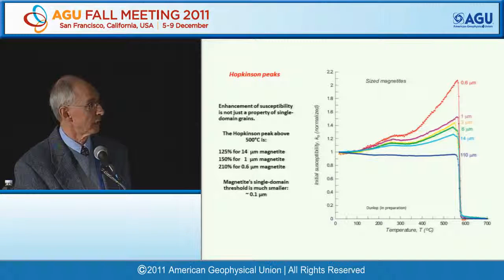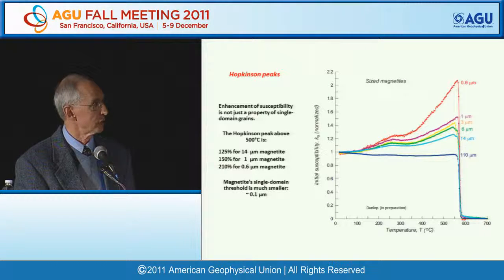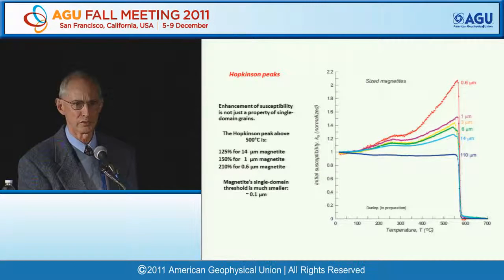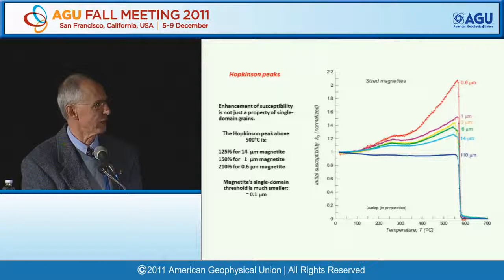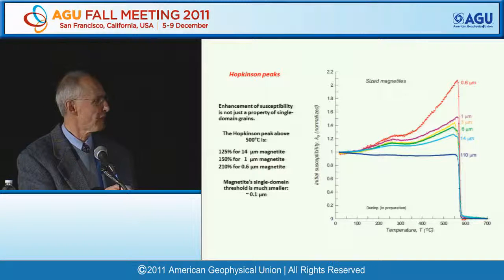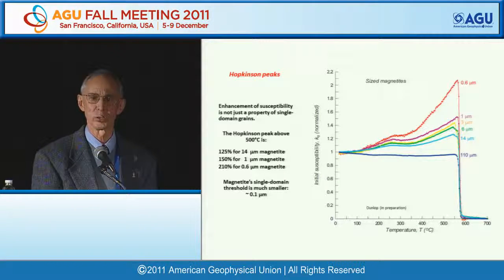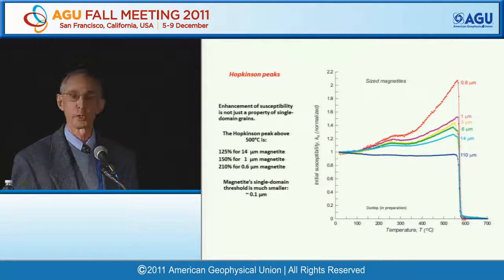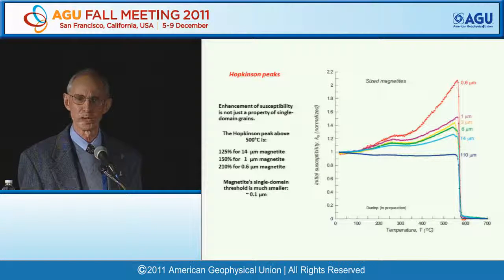But just to stick to the enhancement of susceptibility, that is not just a property of single-domain grains. These data haven't actually appeared in print yet, but I'm very fond of them, and I will publish them fairly soon. You can see that the Hopkinson peak, as it's called, in susceptibility, already for 14 micron magnetites is about 125%, 25% above the room temperature level, 150% for 1 micron magnetites, and over 200% for half micron magnetite, which is still way above the single domain size of magnetite, which is 0.1 micron or even a bit smaller than that. In terms of volumes, it's orders of magnitude above the single domain volume.